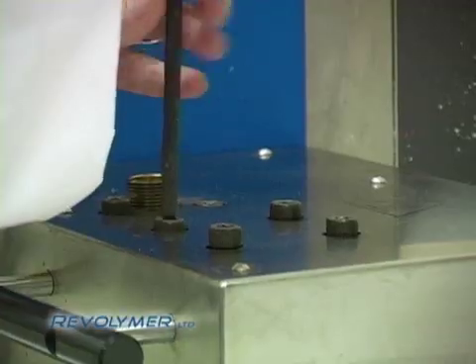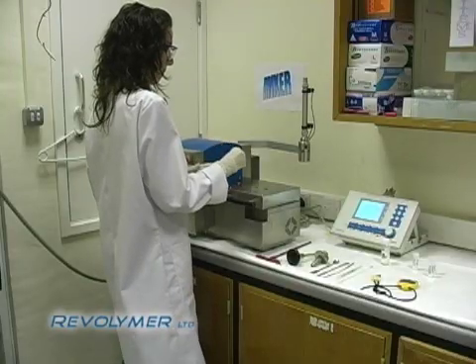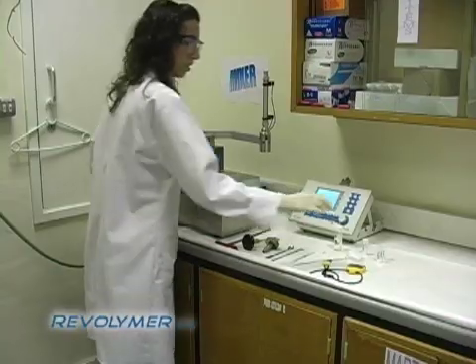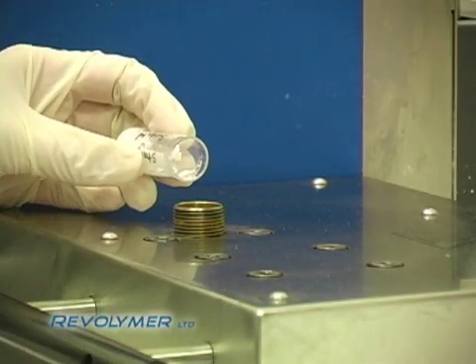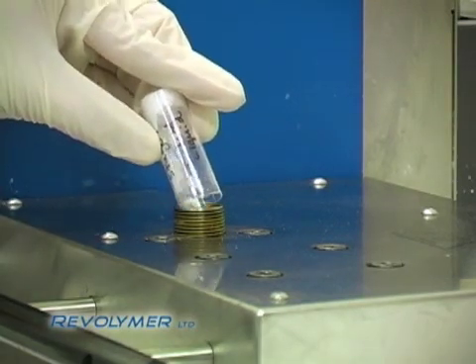When we've closed the machine we add the ingredients to the extruder sequentially. It's important at each stage that the ingredients are mixed homogeneously. We do this in several different phases. It's important not to add all the ingredients in one go because of the natural incompatibility of the materials — this can lead to phase separation and gum failure.